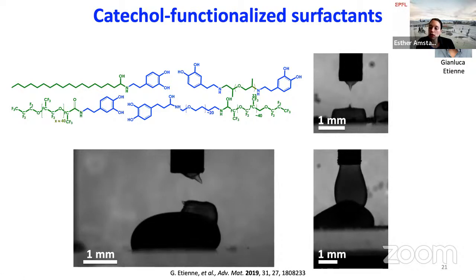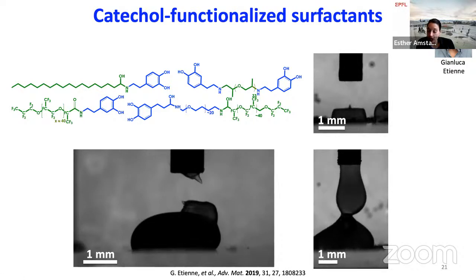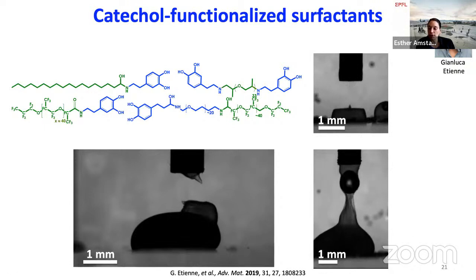And to show that it's actually viscoelastic and that you can exchange reagents between the two different drops, we trapped an air bubble in the sessile drop here. And as soon as the neck that forms between the two drops is large enough, you can exchange this air bubble. You can then separate it again, and they self-heal because of their viscoelastic properties, because the surfactants are only ionically cross-linked, not covalently cross-linked.